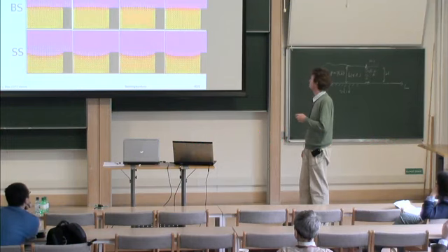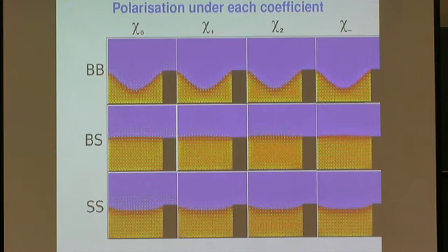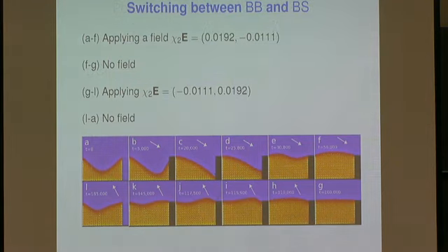And the reason is that the flexoelectric polarization in the corners is of opposite directions depending on whether the distortion is of a bend or a splay variety. If it's a bend, it points out of the corners. If it's a splay, then it points into the corners. And we see that by applying an electric field in a downwards right direction, we are actually opposing the outward polarization at this corner here and causing this region here to shrink. And the interface then moves to the lower corner.